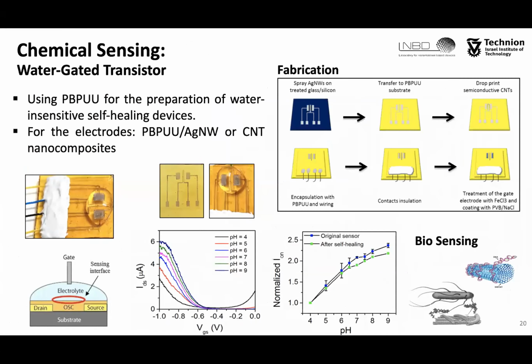For the pH sensor, we used semiconductor carbon nanotubes as the sensing layer, and the device showed higher on-currents under basic conditions. So you can see that the pH sensor was quite successful also in this case.